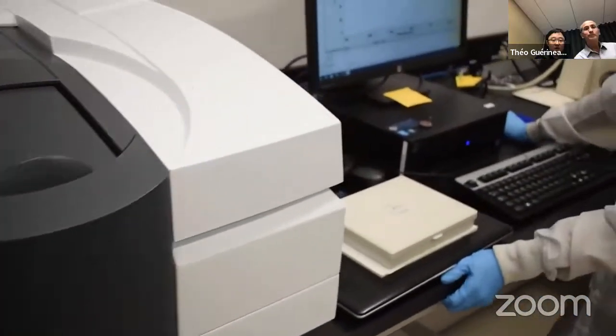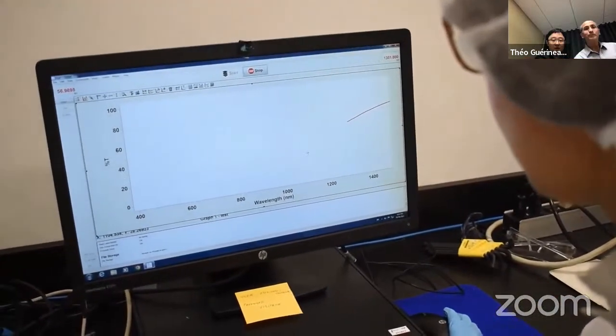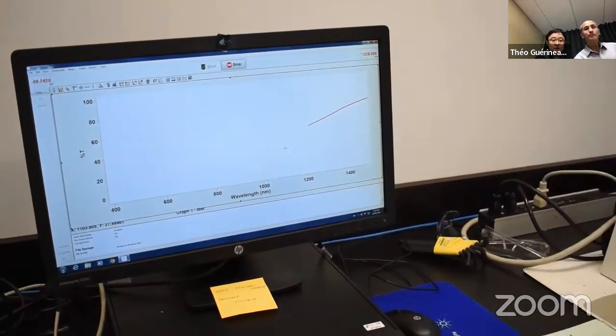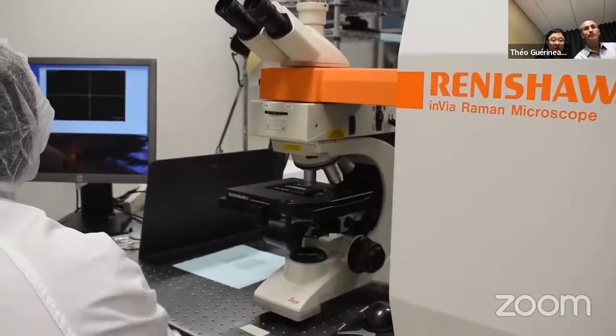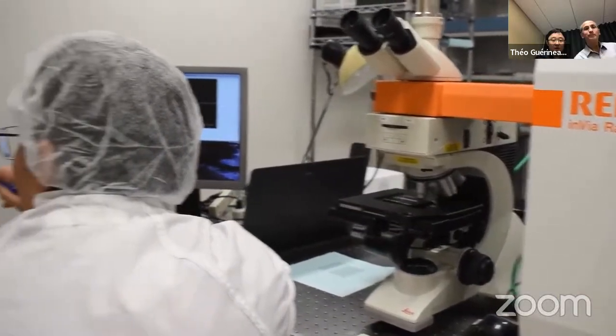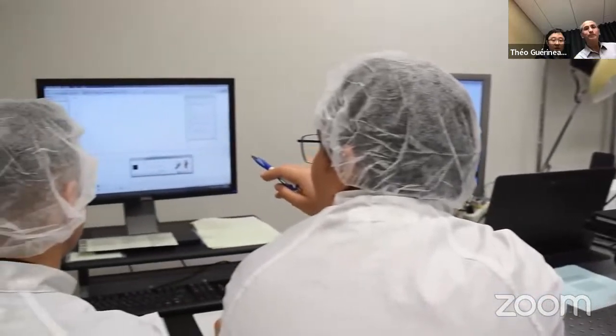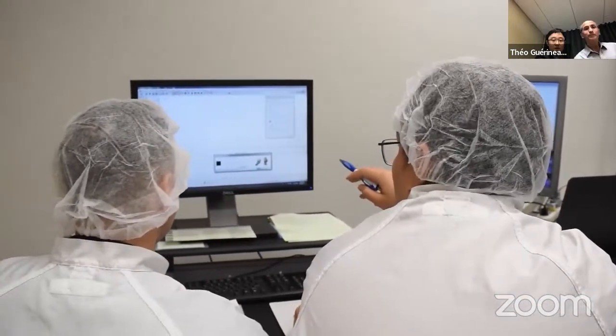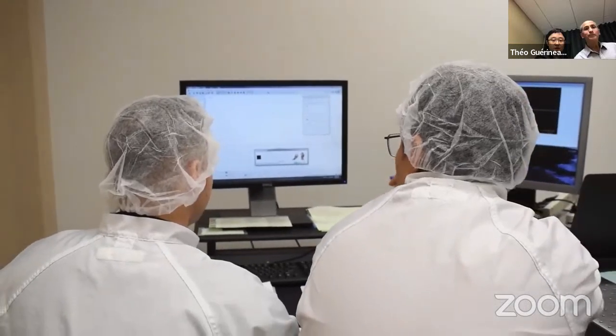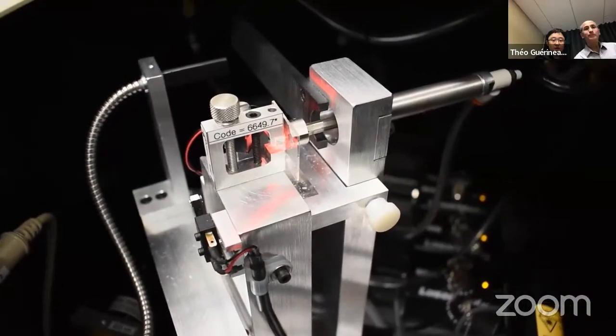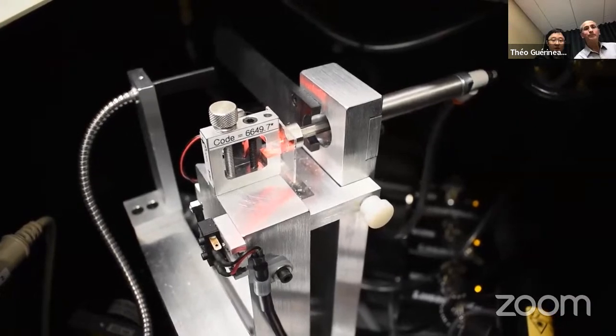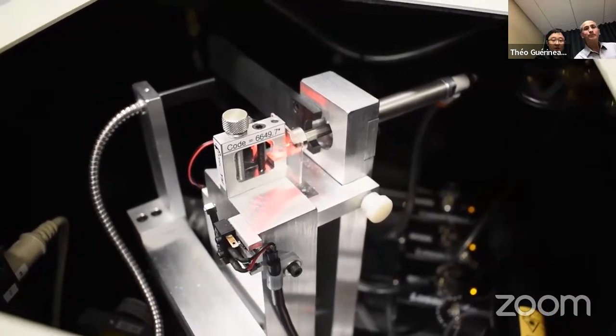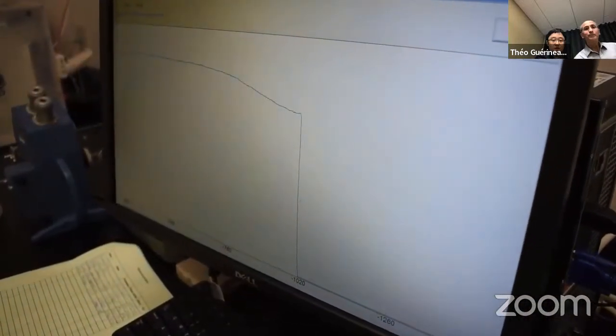We use an ultraviolet-visible-near-infrared spectrometer to measure the light absorption in bulk samples and thin films. Vibrational spectroscopy is performed in a Raman confocal microscope equipped with multiple laser sources and able to map samples at a submicrometric scale. Our group also possesses a high-resolution prism coupler for measuring refractive indexes. An accessory can also be used to couple the light in thin films and measure its refractive index and thickness.